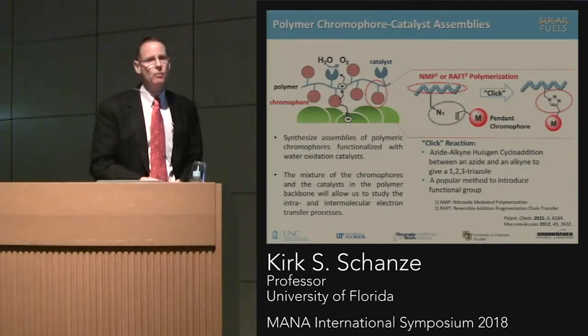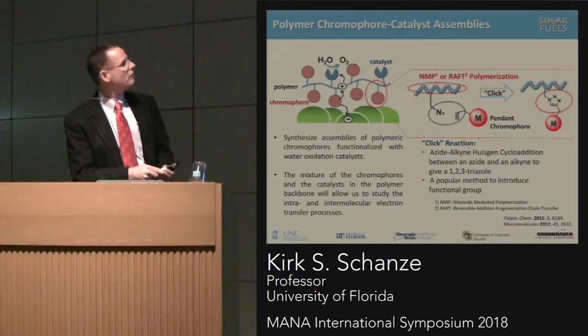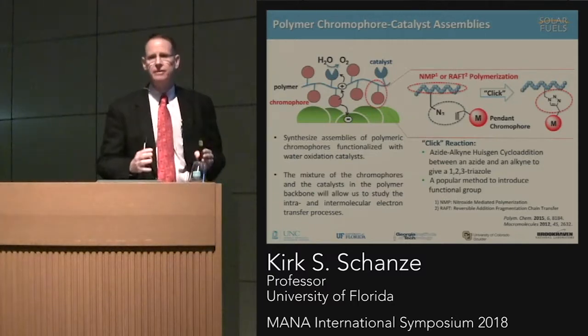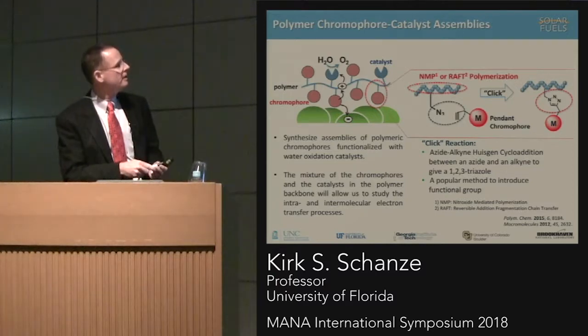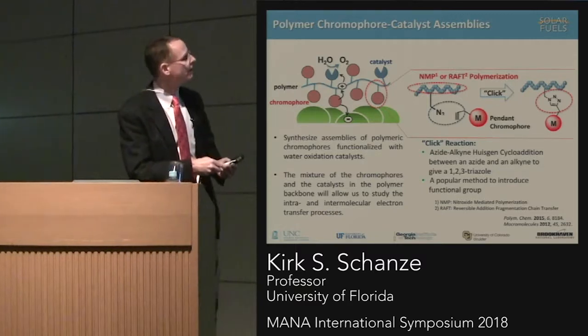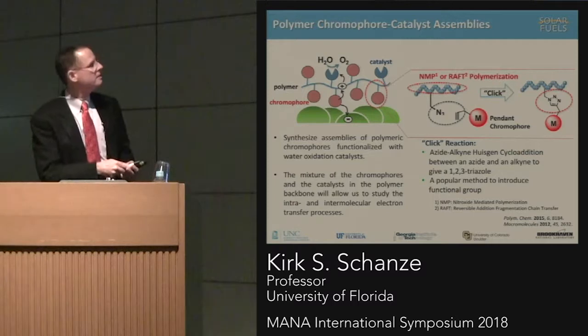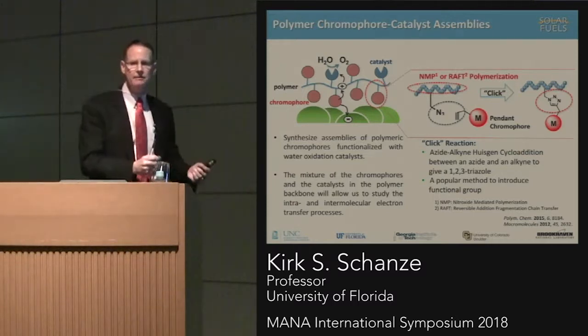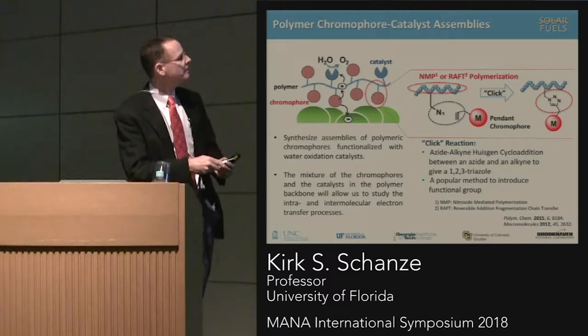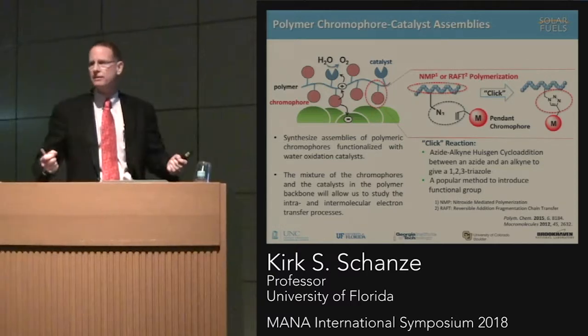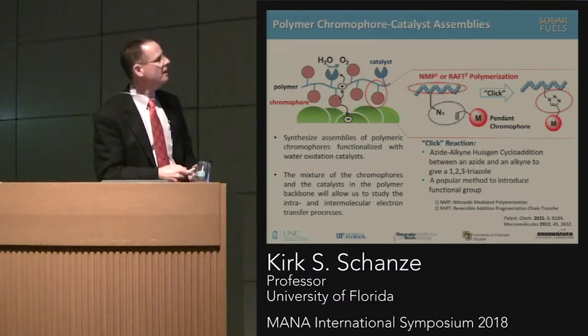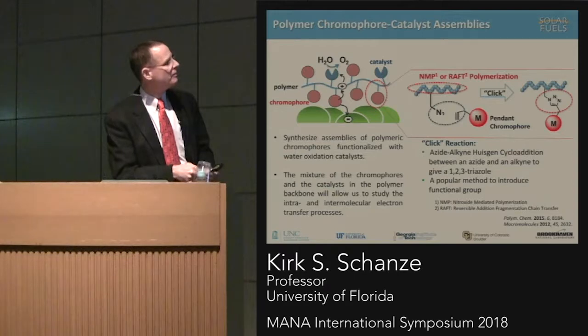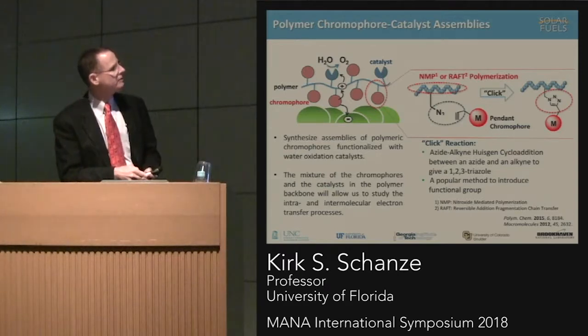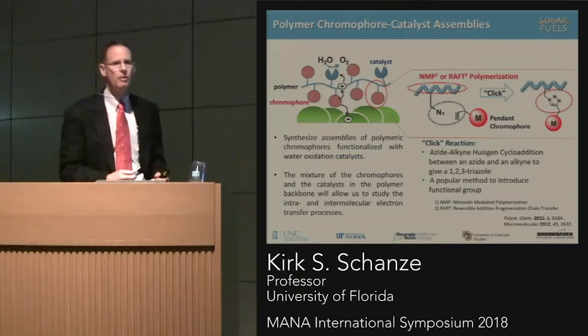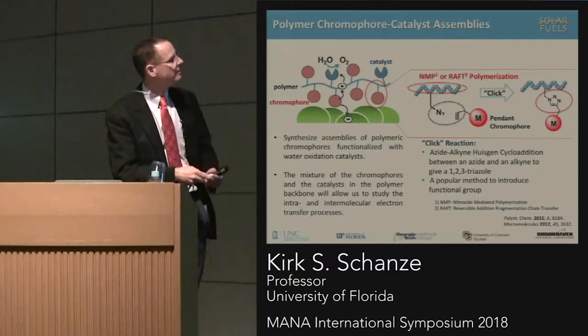Another approach that we've taken quite widely in the center is what we call polymeric chromophore-catalyst assemblies. This approach involves polymer chemistry, and it's shown in this cartoon. The concept is to use a polymer as a scaffold to bring together light-absorbing moieties, chromophores, with catalyst at varying stoichiometry. The beauty of these systems is that we use the polymer as a scaffold to bring together the active components, and using a type of chemistry called click chemistry, well known in the chemistry community, it allows us to mix and match polymers with different components rather quickly. And this has been a big part of our work.